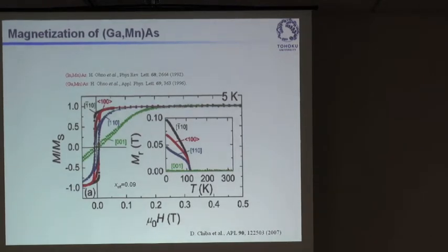Then we measured magnetization. We wanted to see if we have successfully made gallium arsenide magnetic. And indeed, we have seen not only paramagnetic behavior, but ferromagnetic order taking place in gallium arsenide alloyed with manganese. For example, in this case, as you can see, there's nice saturation. The saturation field also depends on the direction of the applied magnetic field with respect to the crystalline orientation. So we have an easy axis, in this particular case 1 bar 1 0, and the hard axis is 0 0 1, the perpendicular axis.